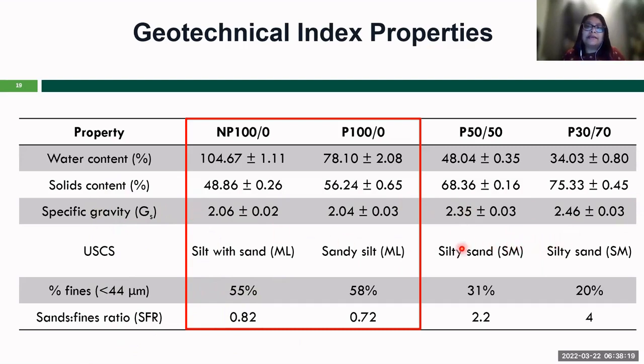Basically, the literature suggests a value around 2.3 to 2.65. But if you look at our 100% non-polymer and 100% polymer data, it is much lower than what we have seen in the literature. However, when we added the sand, it increased because of the presence of sand. But our main focus is on these 2 materials, to compare this data with the literature, and we found our specific gravity is lower than that.